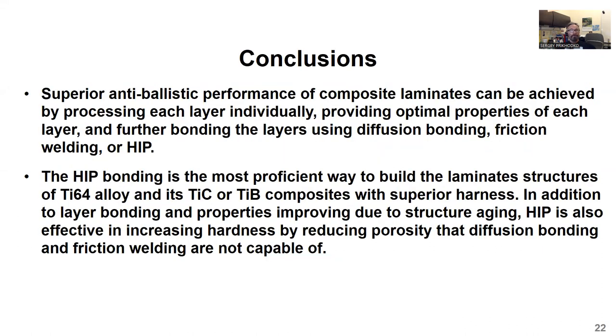Superior anti-ballistic performance of composite laminates can be achieved by processing each layer individually, providing optimal properties of each layer, and further bonding the layers using diffusion bonding, friction welding, or hot isostatic pressing. Hot isostatic pressing bonding is the most proficient way to build laminate structures of Ti64 alloy reinforced with titanium carbide and titanium boride with superior hardness. In addition to layer bonding and properties improving due to structure aging, hot isostatic pressing is also effective in increasing hardness by reducing porosity, which diffusion bonding and friction welding are not capable of.